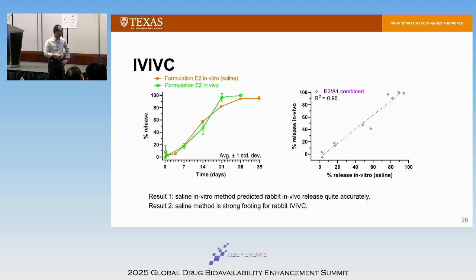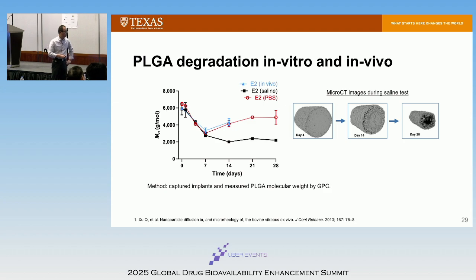And so there are several reasons. We went even one step further. We're looking at polymer degradations. Molecular weight decrease in the normal saline actually matched very similar to what's in the rabbit eye. Okay? So one of the questions is why? We believe one of the fundamental mechanisms is how those oligomers diffuse out. Because those oligomers play a very key role, right? They create a low pH environment, which triggers all these degradations.